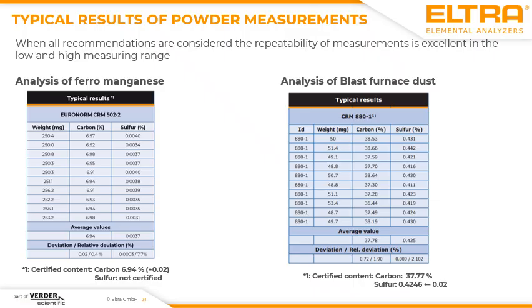The correct application settings in the software, the utilization of the correct accelerator, and the utilization of a fitting sample weight usually cause good repeatability in results. And here we have some typical results which are usually processed as powder, for example, the analysis of ferromanganese with a high carbon content of approximately 6 or 7%, and, for example, dust samples which are applied with a sample weight of 50 milligrams and even a higher carbon content of 37%. So when you are using iron and tungsten as accelerator and set the application settings to a dusty sample, you can get repeatable results like this.